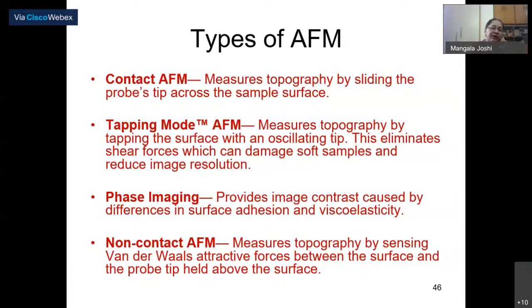And then there is a non-contact mode where you don't touch the sample, the tip doesn't touch the sample, but it measures the topography just by sensing the attractive forces between the surface and the probe tip held above the surface. Then you have a phase imaging technique where it provides image contrast caused by differences in surface adhesion and viscoelasticity. So these are very, very useful techniques.